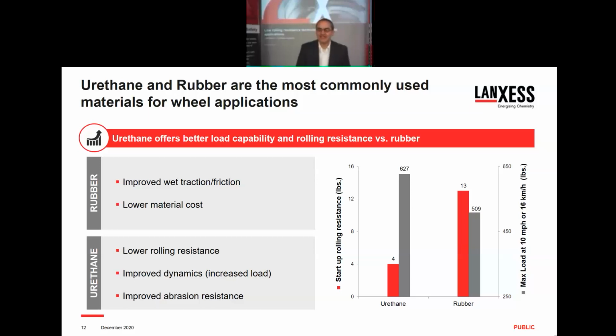The red bar is the actual rolling resistance. In this case, lower rolling resistance means less force to roll the wheel, so lower is better. The gray bar is actual load capacity at 10 miles an hour. In that case, higher load capacity is what we're looking for. And in this case, what you can see is the urethane is roughly a 3 times improvement in terms of rolling resistance. And this is per wheel for the specific application that we were looking at. And the load capacity is significantly higher at 10 miles an hour. Again, same hardness, 75 Shore for both of these.